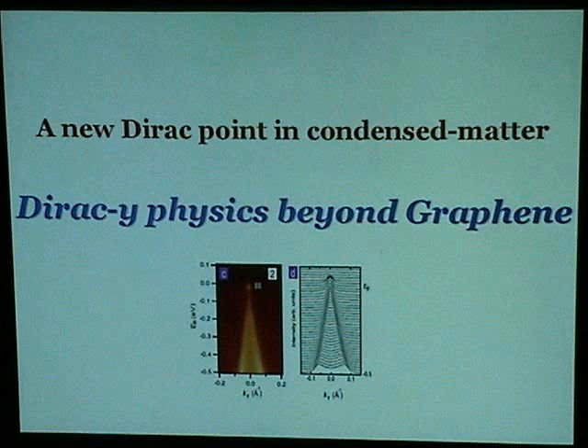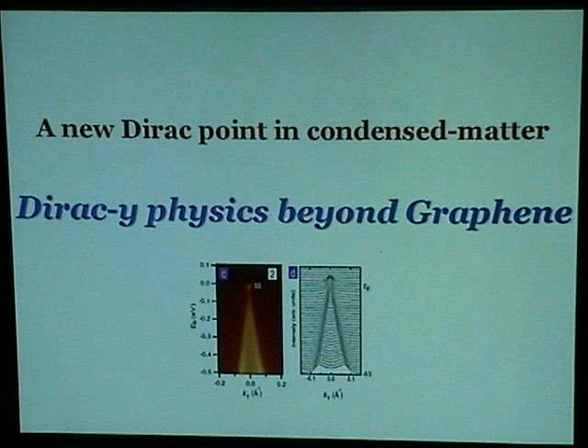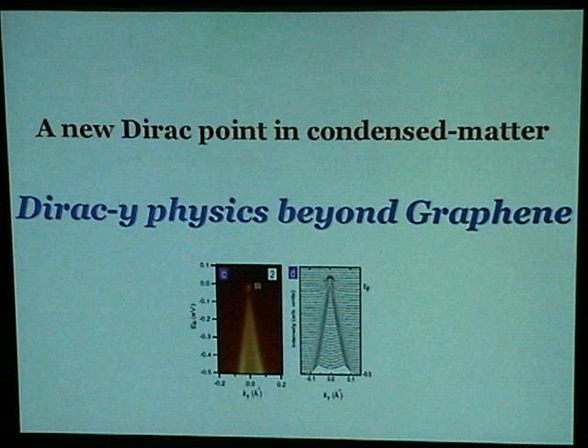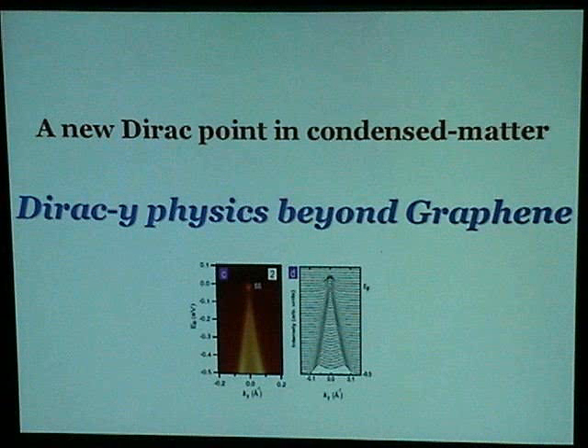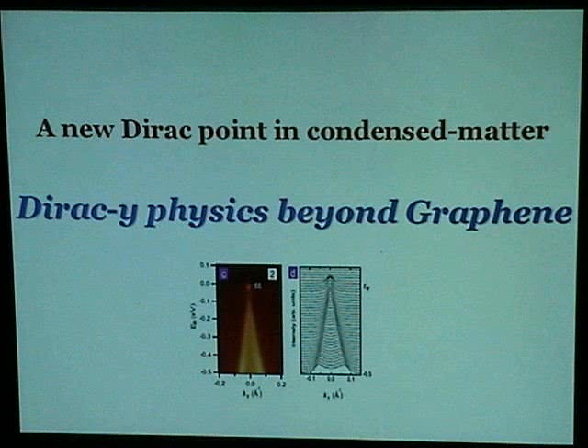Does it have large thermal power? Yes, it has large thermal power at low temperature. Oh, how about high temperature? At high temperature, large thermal power is in all doping. It's not specific to this particular composition. So it's almost classical thermal power. Yes. Actually, no, it's more than that. It's 10 times more than the classical thermal power. No, it's classical in the sense that it's kB over e, not suppressed by temperature or something. Right, it saturates to some value. It's close to the classical value.